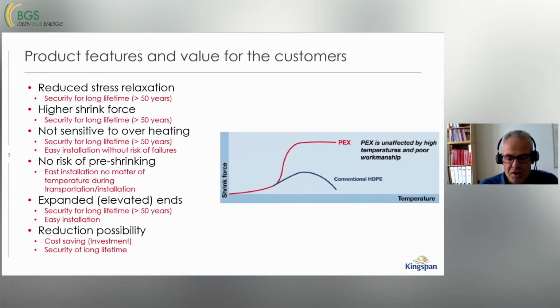The cross-linked joints have a lot of very strong features that create very strong values for the customers. And our customers are mainly the energy companies that are the owners of the pre-insulated pipe systems in the ground. I will, in 2 short videos later in my presentation, show you the features. But just to highlight a couple of the features you see on this slide: when we have cross-linked materials, it's not sensitive to overheating. So even if the material is overheating, it will keep the shrink force.